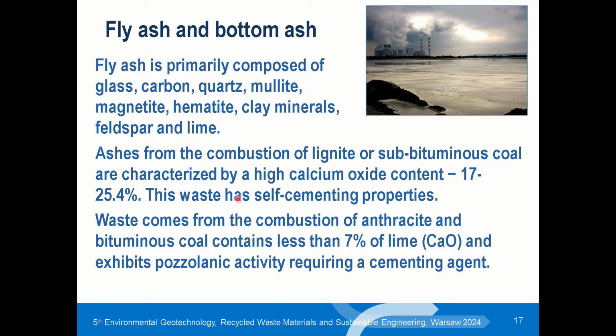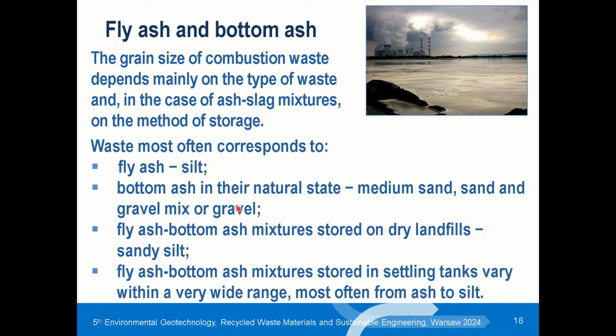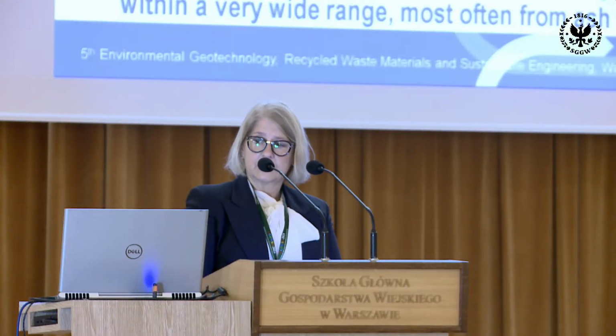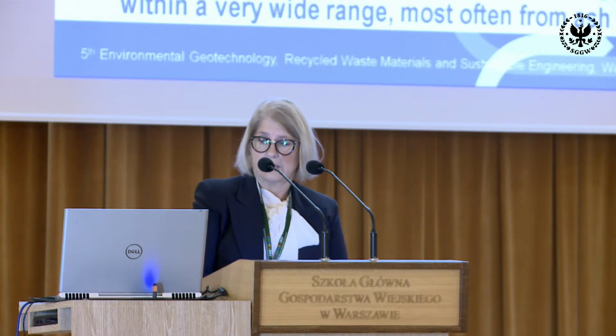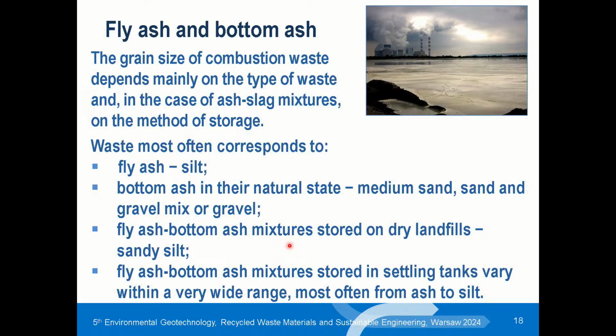Waste coming from combustion of anthracite and bituminous coal contains less than 7% of lime, and exhibits pozzolanic activity requiring a cementing agent. The grain size is different. It depends on the kind of waste. So fly ash corresponds to silt. Bottom ash in the natural state corresponds to medium sand to gravel or a sand and gravel mix. But for a fly ash and bottom ash mixture, the graining depends on the technology of storage and kind of landfill. It is a landfill or it is a wet reservoir.